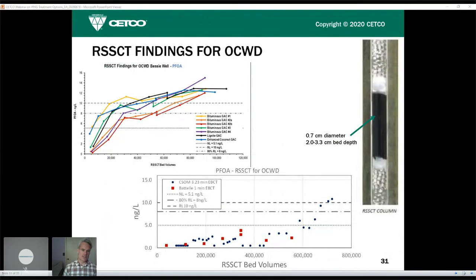These are some results from rapid small scale column tests. The idea behind a rapid small scale column test is you grind the media down to a predetermined size and run it in small column systems. And the idea here is that you can screen a wide variety of media for removal performance in a relatively quick amount of time. So this top figure on the left is showing some results from different GAC products in terms of PFOA effluent concentrations.